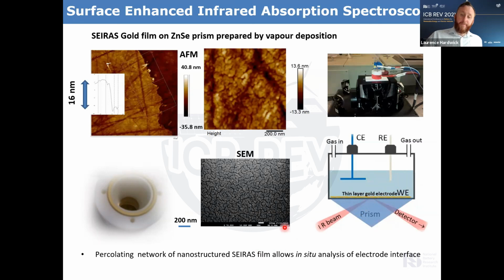So we bring the beam in from below our cell here. So we can see our cell sitting on our optical device. Our infrared beam is brought up here and then reflected back down. Because of our configuration, we're only really probing the first 10 nanometers thick of this layer within the electrode surface. And so we have this cell which is set up specifically for looking at oxygen electrochemistry, which is pertinent to metal oxygen batteries.